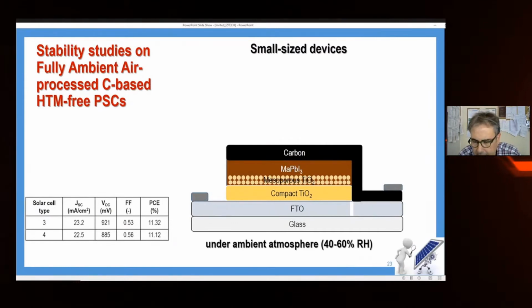I referred before to stability. If you have this device, of course, we may understand we cannot expose it in the atmosphere under real conditions of continuous illumination and humidity and so on, and expect after 1 year a good performance. It is something impossible. That's why we need to isolate this structure from the environment, and the method that we usually follow is the following here. We have an encapsulation method to make this device stable for all the tests that are needed to be passed before we go to commercialization.